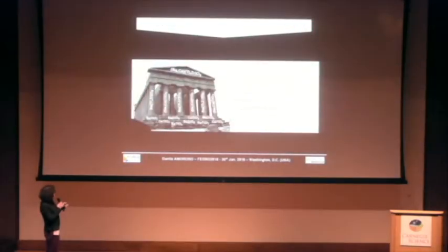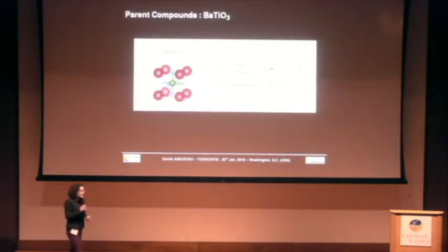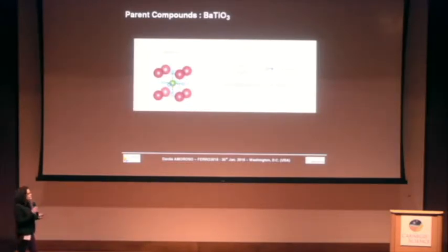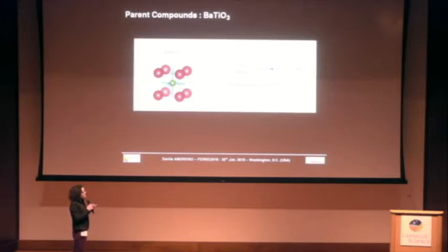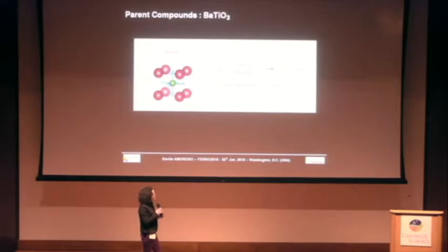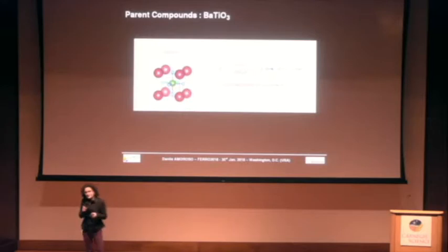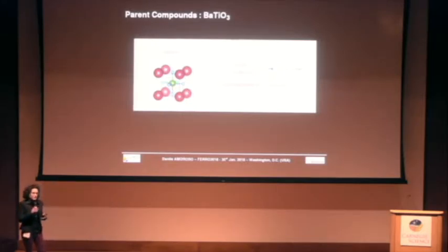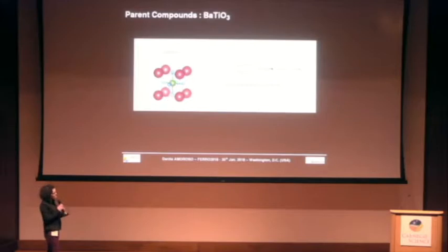And so the big boss here is, as we know, BTO, that we have seen widely is characterized by two main factors. The one is that the tolerance factor is bigger than 1. That means that the B site, so the titanium, is small enough to off-center in order to improve the bonds with the oxygen with respect to the ideal cubic perovskite structure. And accordingly, the destabilizing interaction that sustains these instabilities, this distortion, is occurring between the titanium and oxygen atoms.